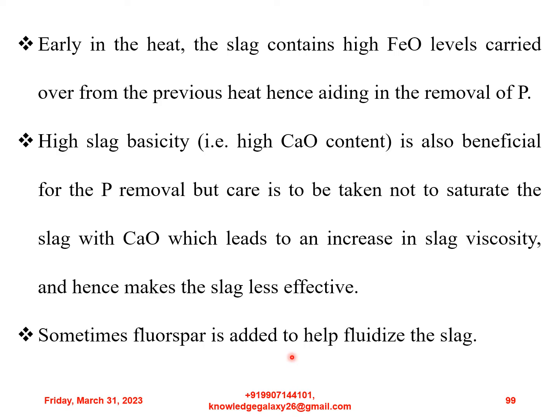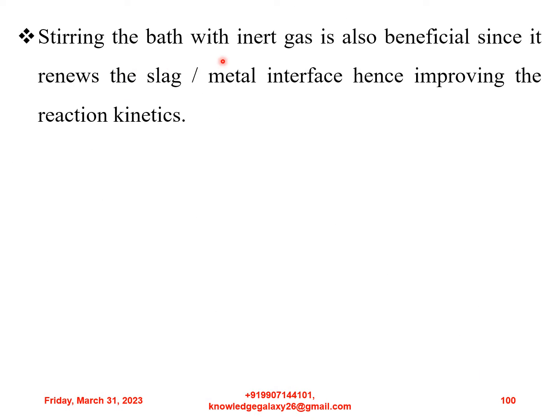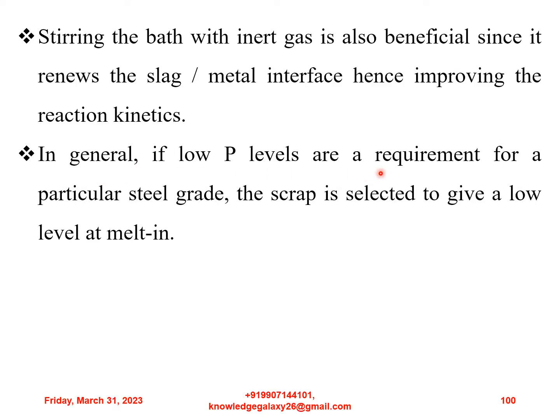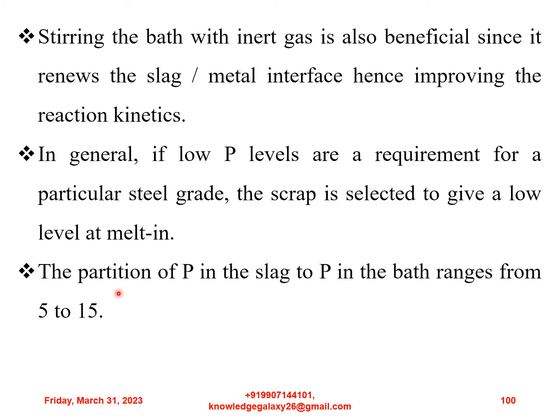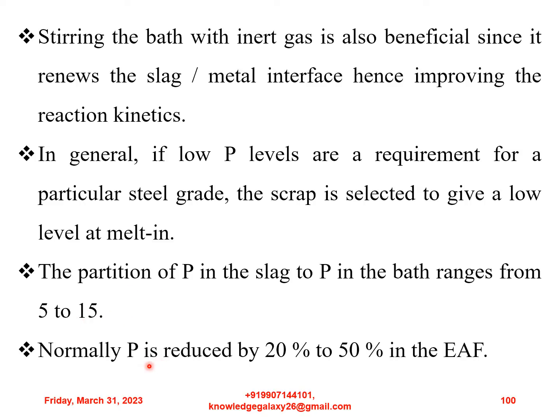Sometimes fluorspar is added to help fluidize the slag. Stirring up the bath with inert gas is also beneficial, since it renews the slag-metal interface, hence improving the reaction kinetics. In general, if low phosphorus levels are a requirement for a particular steel grade, the scrap is selected to give a low level at melt-in. The partition of phosphorus in the slag to phosphorus in the bath ranges from 5 to 15. Normally, phosphorus is reduced by 20% to 50% in the electric arc furnace.